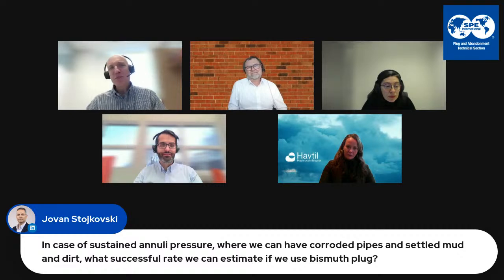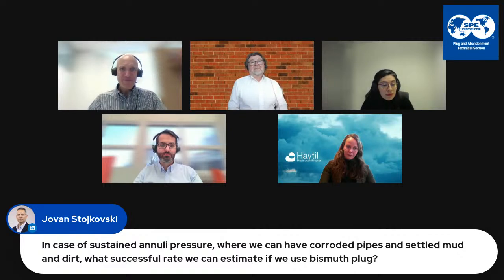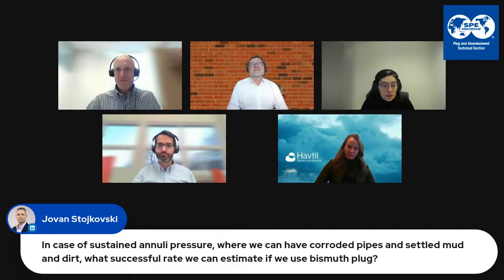Maybe it's a question for Martin also, in the real application case. Yeah, it's a good question, and it's difficult because it depends on how much, if there is a hole corroded directly through the casing. If that's the scenario, then you will probably be best off to set the bismuth across there, or actually below it, if possible. If you set it below, then you'll stop the leak. If you set it above, it doesn't do you any good. So either across the leak or below, if possible.